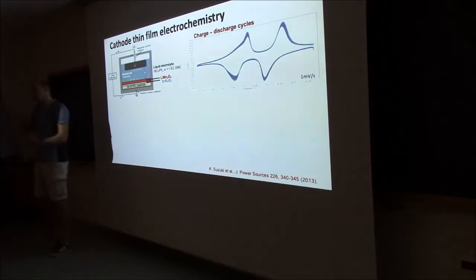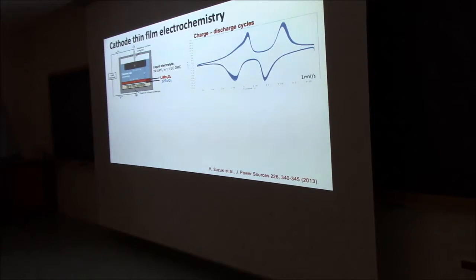But the problem was the band alignment between the spinel material and the conducting STO substrate, which was niobium doped. We were not able to get the electrons out. And people showed that if you put strontium ruthenate in between, that was better. So in the first starting point, we said, okay, let's do that.